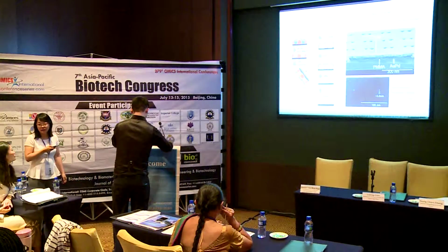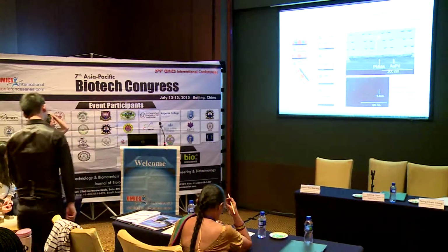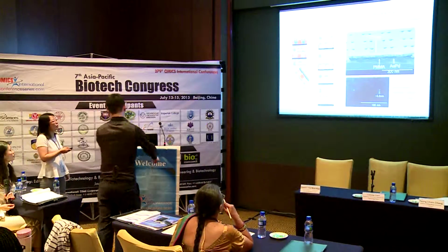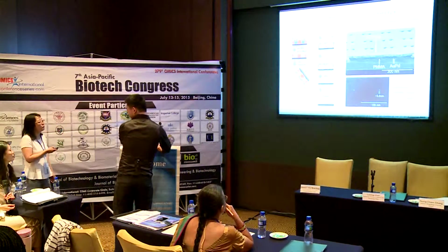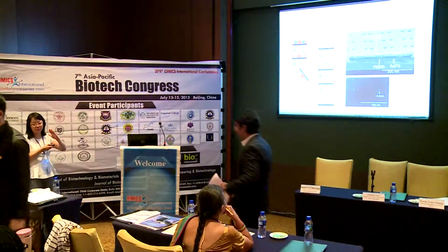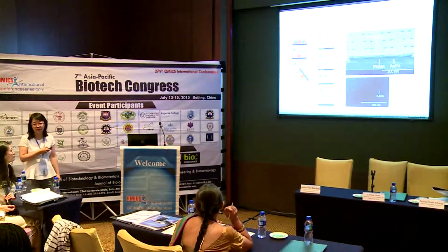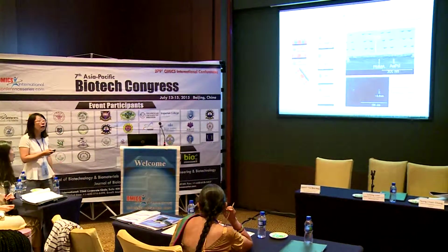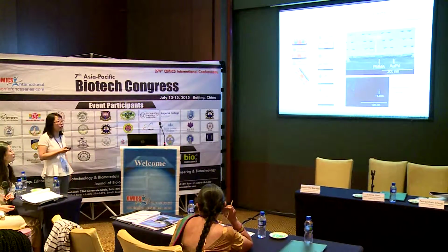It's a silver pattern. Yeah, we use titanium to transfer the pattern. We use titanium angle evaporation to decrease the dot size. With e-beam lithography alone, we can only make patterns of about 20 nanometers. But using this method, we can go down to 3 to 4 nanometers.